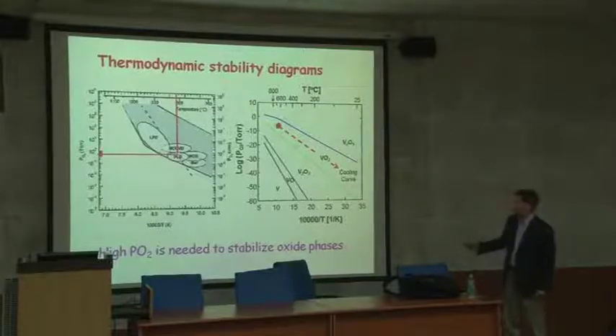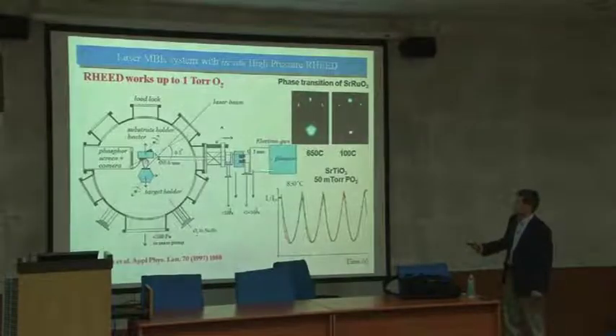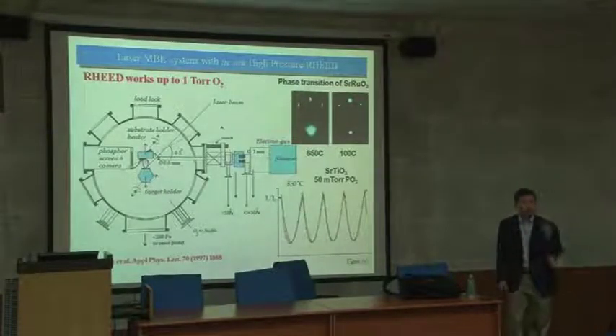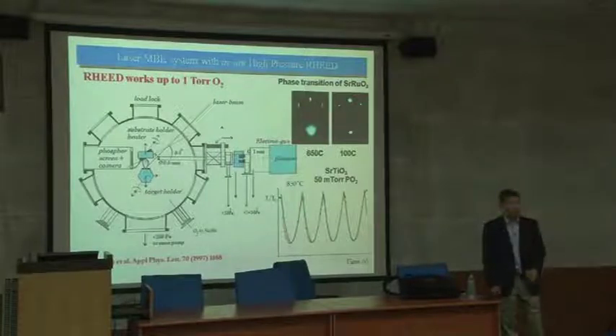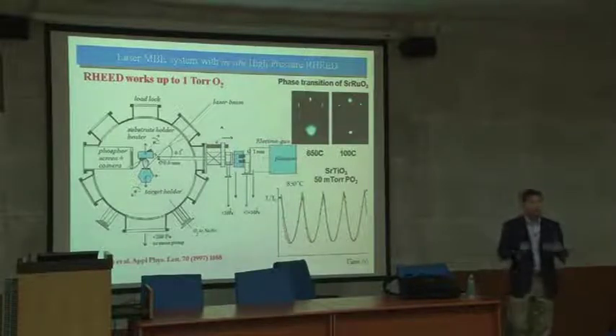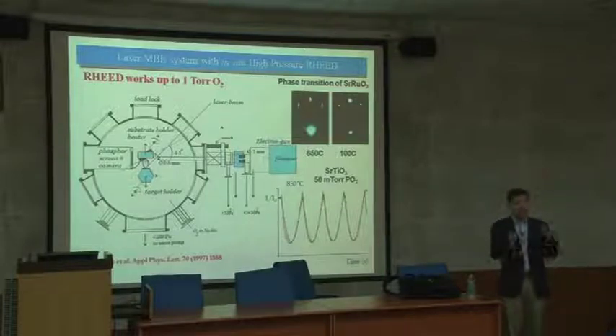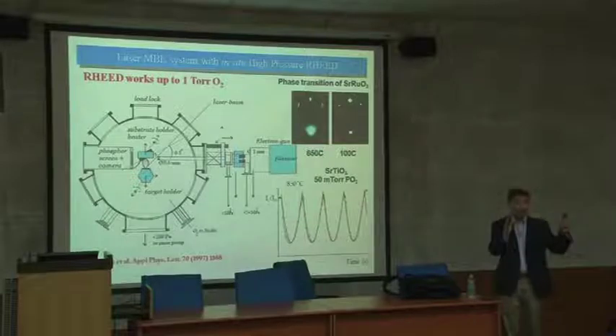And in order to do that, you can see this RHEED gun has two problems. One problem is how you can generate electron beams. Anybody know how to generate electron beams? The electron beam is simple thermionic emission. You heat up a high temperature filament, and the electrons overcome the vacuum level, and electrons come out, and you accelerate them from the electric field.